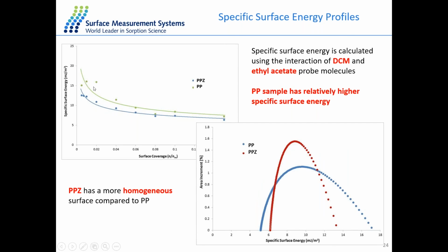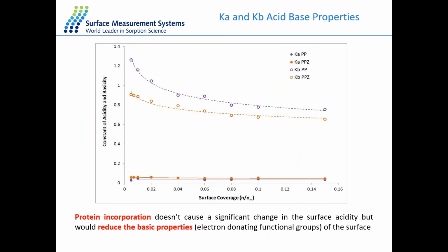We've also calculated the specific surface energy. In this case, we've used dichloromethane and ethyl acetate as polar probe molecules. And what we can see here, again in the same trend, is that the polypropylene with the zein protein has a lower specific surface energy compared to the polypropylene on its own. And looking at the infinite dilution region, we can see that the polypropylene has a larger peak width and therefore is still very heterogeneous. We've also calculated the Ka and Kb. This is the acid and basic properties of the material. What we can see is that the protein incorporation doesn't cause a significant change to surface acidity, but it would reduce the basic properties. So this is looking at the electron donating functional groups on the surface.